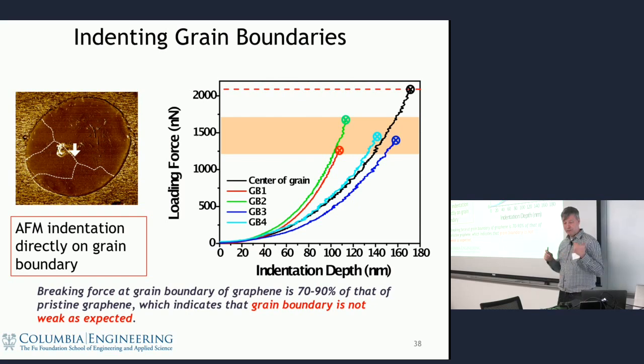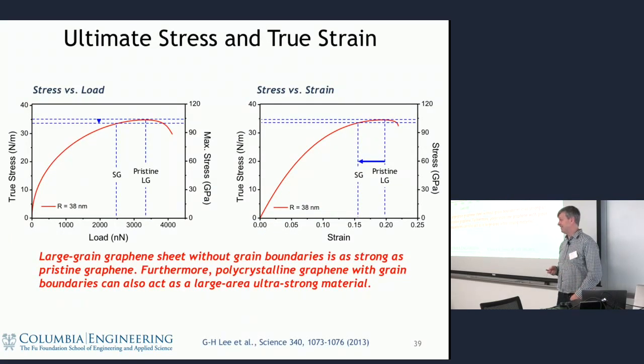So the nice thing is, we could be a little bit more quantitative now. Instead of just talking about the fracture load being 30% less, we can now do the simulation of the experiment and talk about the fracture strength. And so that's where this nonlinear model comes in. We do the nonlinear modeling, and because we can now take any tip we want, any geometry we want, we can generate a plot of stress underneath the tip as a function of load. And what we could see is that if we take either the pristine or large grain, and look at the decrease in fracture load for small grain, it only corresponds to about a 5% decrease in fracture strength.